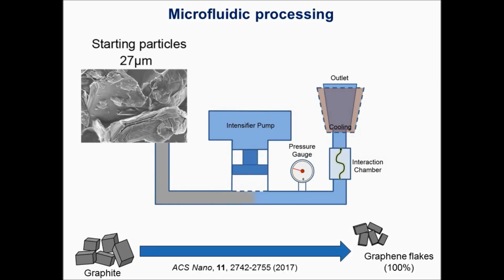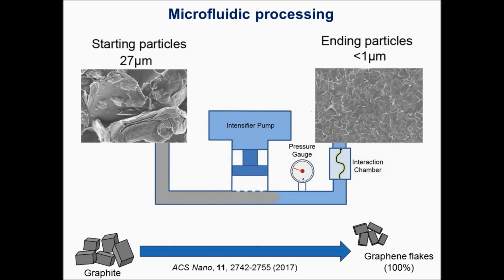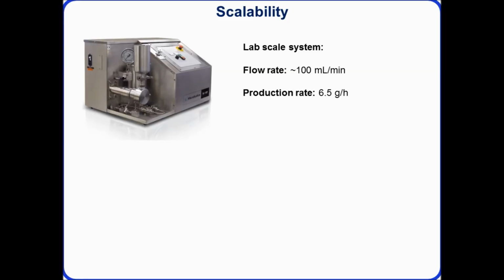The particles we put in are around 27 microns, and after 70 cycles they're around 1 micron in lateral size. So they go from bulky rock-like structures to very thin platelets. One of the interesting things, and the most promising thing, with the microfluidic processor is the scalability. With our lab-scale system, where we have flow rates around 100 mL per minute, we're producing around 6 to 10 grams of graphene per hour.